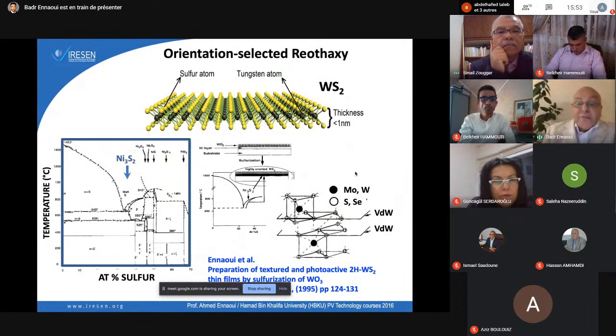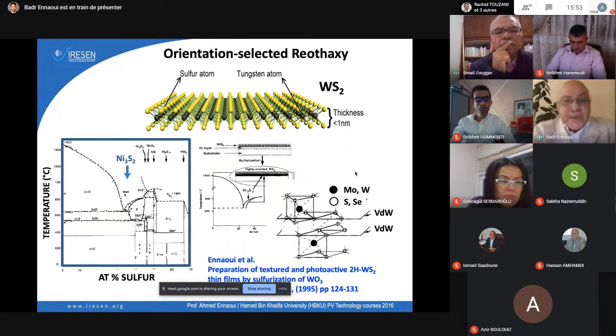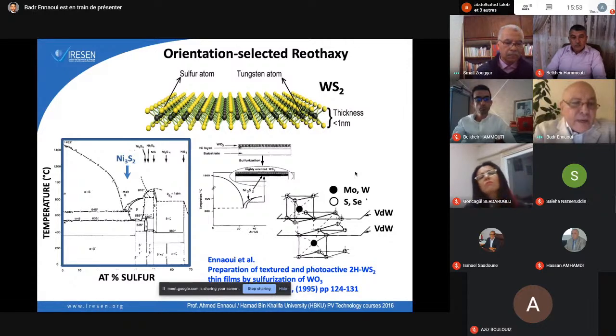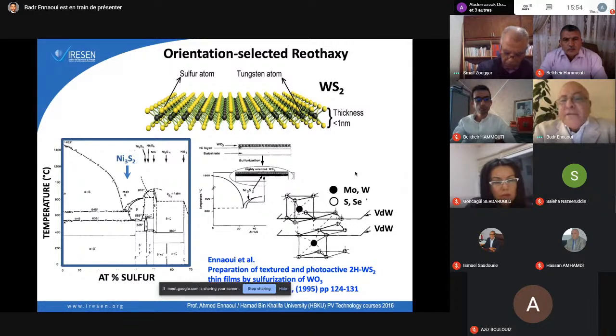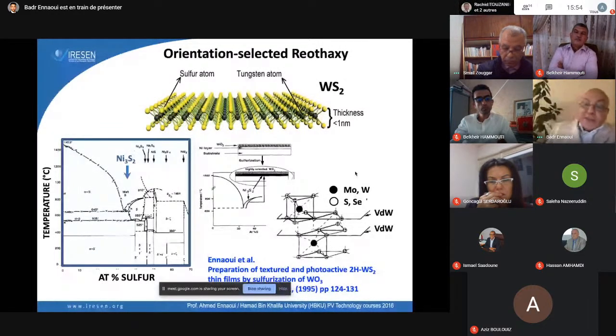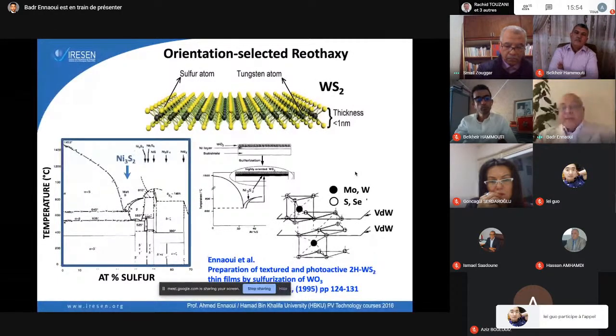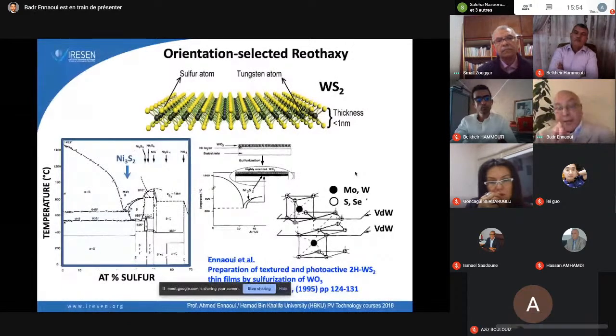Another topic that I started long ago is to use ink at high temperature. I give you just one example here. Nickel sulfide melts at around 600 degrees. And if you, for example, prepare tungsten oxide and you deposit some nickel sulfide on it by drop on demand, and you do annealing, you will transform your tungsten oxide into a layered material like tungsten disulfide, but with very highly oriented material. So your material will grow according to the van der Waals plane, so the surface of your material will not show tungsten, which is a recombination center. And this is very important.